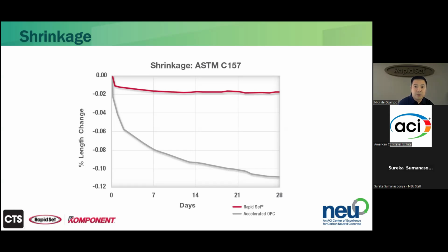This chart here shows a comparison between two rapid hardening concretes, so we're still talking about speed, following ASTM C157. This is a quantitative way to measure the amount of length change going on in a concrete specimen. So the rapid set concrete, the red line up at the top, exhibits less than 0.02% shrinkage at 28 days. And I believe it's ACI that says the threshold for cracking is at 0.025. So if you're under 0.025, it's expected that material is not going to crack, or at least not at that time frame.